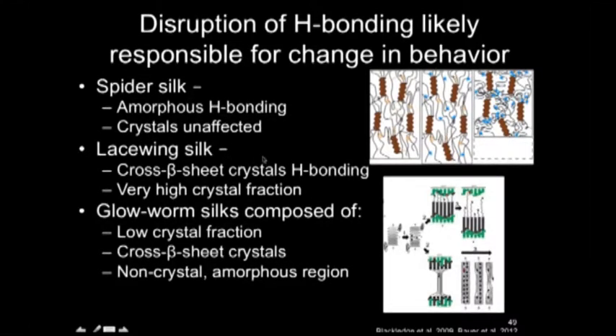And there are several examples of this in spider silk, lacewing silk, as I showed, as well as in glowworm silk, where, and I'll show this later, their nanocrystals are oriented in a non-parallel direction to the fiber axis. And the idea is that they unfold similar to lacewing silk, where water actually penetrates the bonds between these beta sheets. And rather than stretching like spider silk, where the beta turns and alpha helices stretch, the crystals also unfold in both lacewing silk and glowworm silk, whereas in spider silk it does not. And this is a really unique behavior that has been hypothesized, but yet to be fully proven.